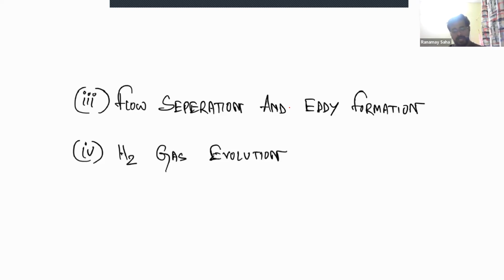Now as some portion of the electrolyte separates, it may take away a larger concentration of metal ions, and this can result in a higher concentration of metal ions building up in the electrolyte at some parts, and comparatively lower ones building up at some parts. Okay, so there can be concentration overpotential in the eddies at some points of the electrolyte, and this can introduce a localized variation in the removal rates, right? So probably this variation in the removal rates can lead to irregularities in the surface, and you may not have a uniform surface finish throughout the work.